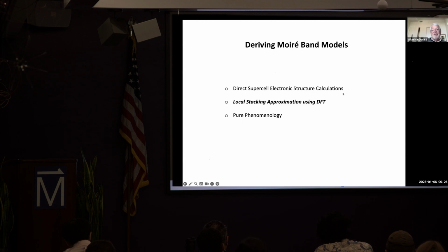In other words, anytime I have a moiré material for a generic twist angle theta, the real underlying system is not periodic, is not crystalline, but there will always be a discrete set of twist angles for which there is some long spatial period, a very small reciprocal lattice vector, much smaller than the moiré reciprocal lattice vectors, which form a lattice. And so you can just do a direct calculation of the Hamiltonian of such a large supercell, and that will tell you what the terms are in the Hamiltonian at the moiré reciprocal lattice vector wave vectors. That sort of method is one way to calculate what these Hamiltonians are.